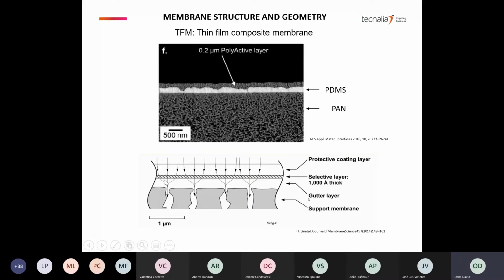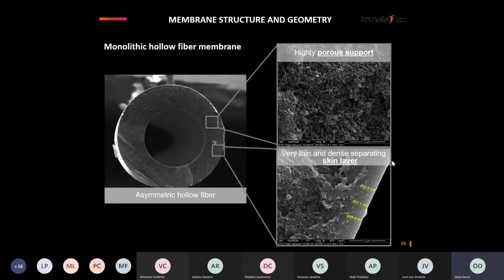Then the other objective is that it makes a much smoother surface. Therefore the selective layer can be very thin, about 100 nanometers thickness in a commercial layer. And then there can be an extra layer, which is a protective coating layer. So to make this kind of architecture, it's a multi-step process and can be quite complicated.